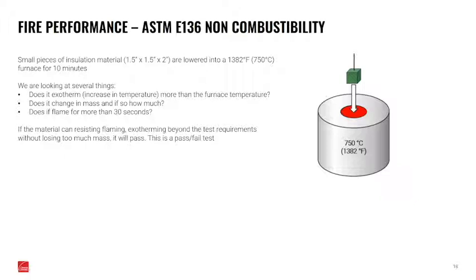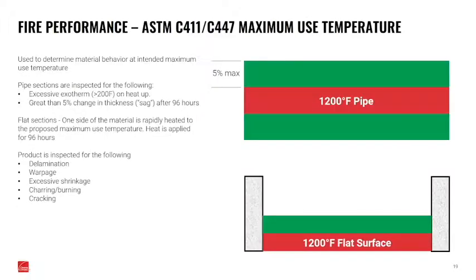Or what if it flames for more than 30 seconds? It could almost be considered a fuel source at that point. Those are the things that we want to know. This is one of the few fire tests where it's a pass-fail. Usually a test is just a test until you apply some criteria to it as to whether it's a good or bad result. But in this case, if you exceed the maximum exotherm temperature, or you lose too much mass or too much flaming, you just fail the test.